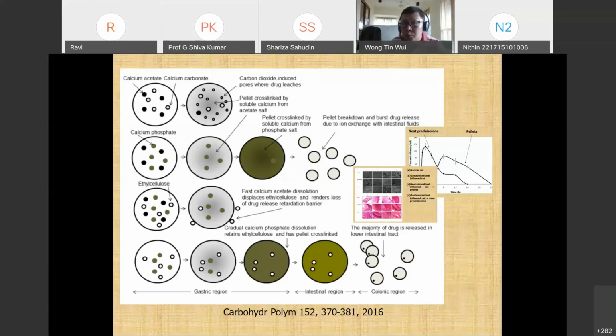Now, calcium phosphate is a moderately water-soluble calcium salt. It will be solubilized only gradually, and this gradual solubilization of calcium phosphate is very important because it will sustain the alginate matrix through formation of a calcium alginate structure. And this structure will be rather robust across the gastric and across the intestinal region. And it is only when the whole matrix enters the colon that the structure will be broken down into smaller particles for site-specific drug release.